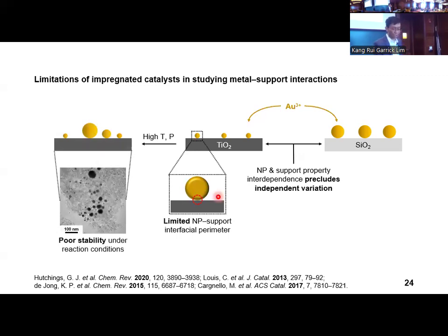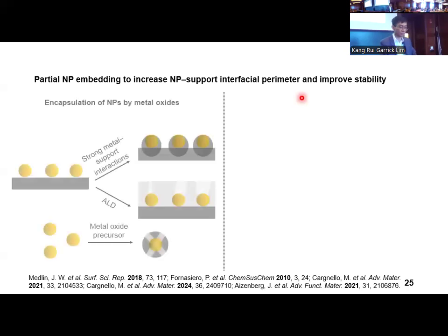Third, under thermocatalytic conditions of high temperature, pressure, and mechanical agitation, these impregnated catalysts are prone to nanoparticle leaching and sintering, which further confounds our catalytic analysis. To address these limitations, we, together with other researchers, have identified partial nanoparticle embedding into the support as a key design feature to increase the nanoparticle support interfacial length and improve catalyst stability against sintering.